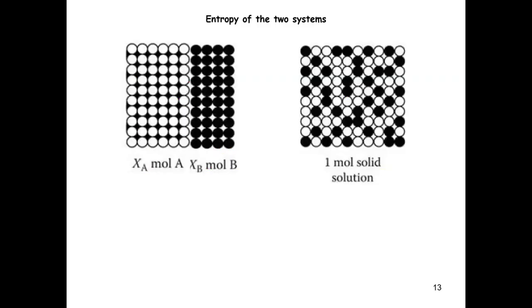So now go back to this, right? We spent some time to describe this. Still, we need to keep in mind that when we talk about these solids, they're vibrating, but the vibration contribution for this state and this state are the same, so they cancel one another. So we don't have to really take into account. Now the only thing that we need to consider is the contribution to the entropy due to distinct atomic configurations or atomic packings, namely the small omega. Does it make sense to everyone?